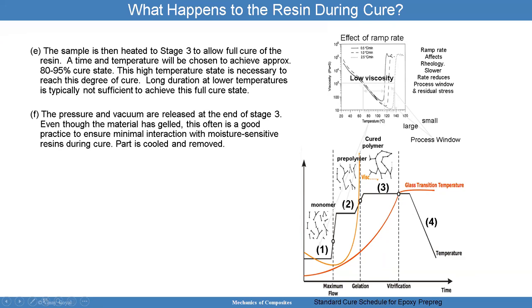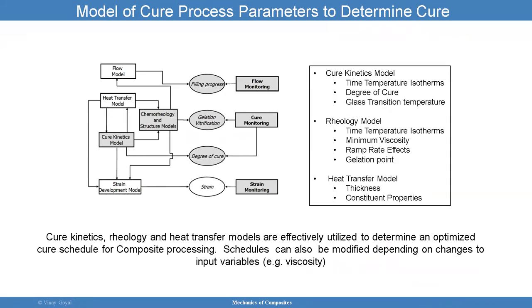So the pressure and vacuum are released at the end of stage three. And even though the material has gelled, this is often a good practice to ensure minimal interaction with moisture sensitive resins during cure. And now I'll cool the part. And once I cool it and it's not hot anymore, you can remove it and you're ready to use the material.